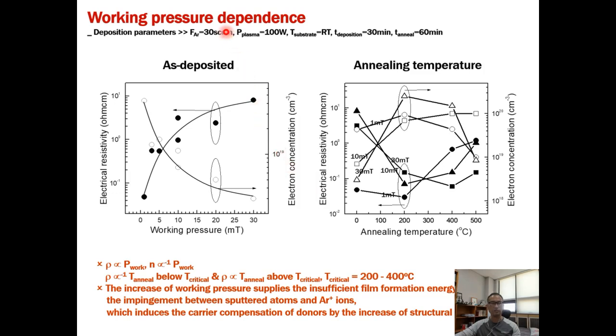Second, I will show working pressure dependence. In the left figure, electrical resistivity increases with working pressure. Electron concentration is vice versa. In the right figure, electrical resistivity decreases with the increase of annealing temperature until about 300 degrees centigrade. Above 300 degrees centigrade, it has a tendency to increase. Electron concentration is vice versa.